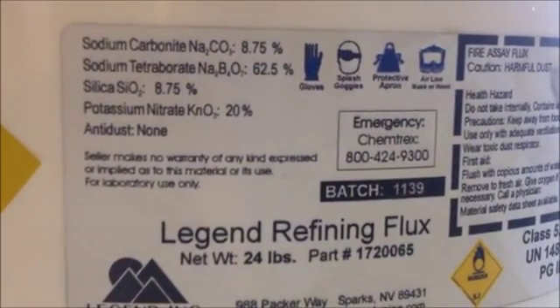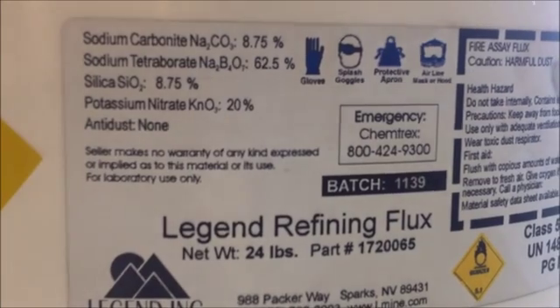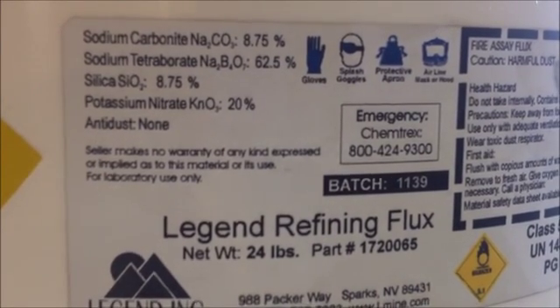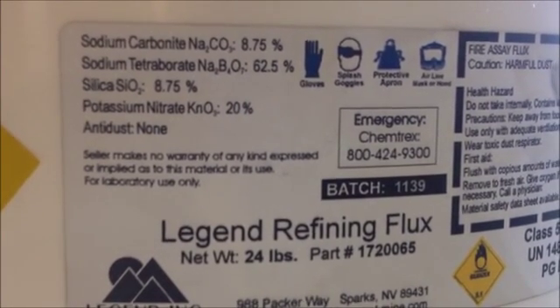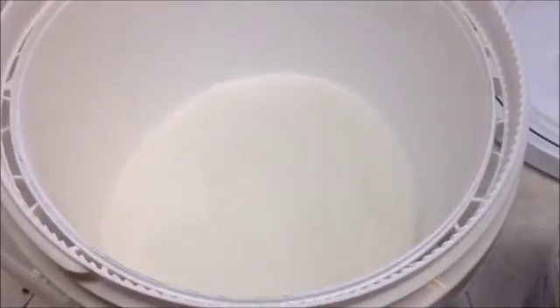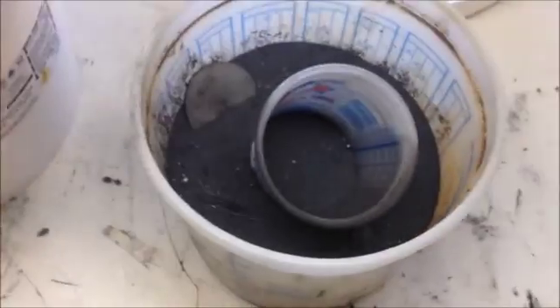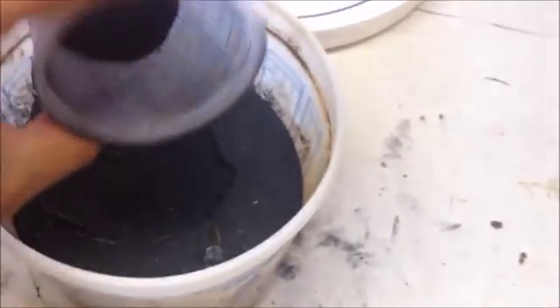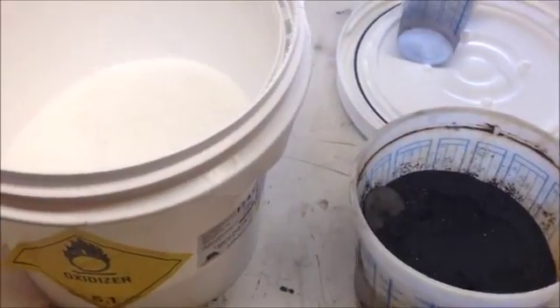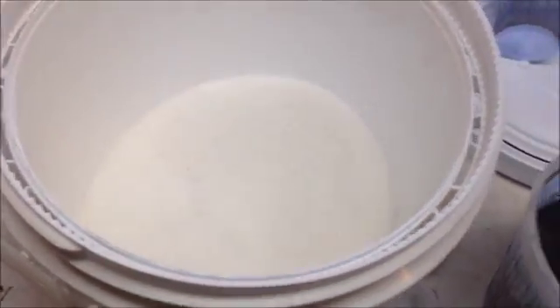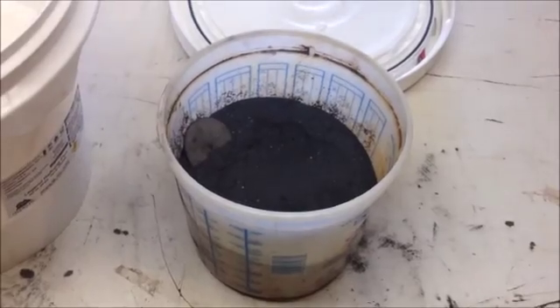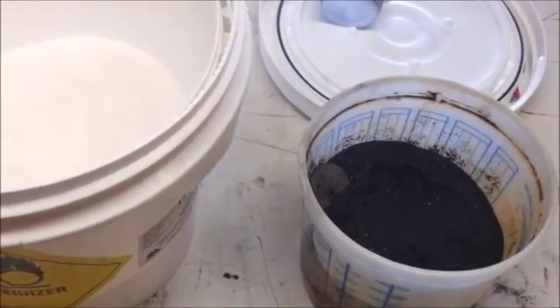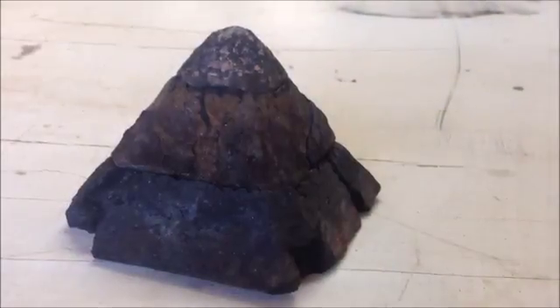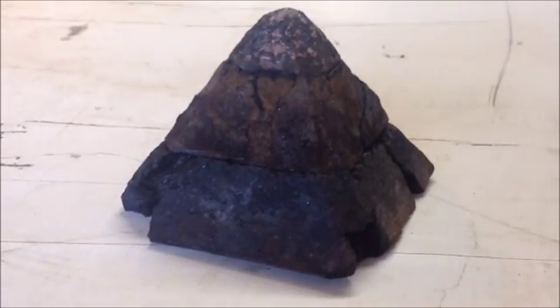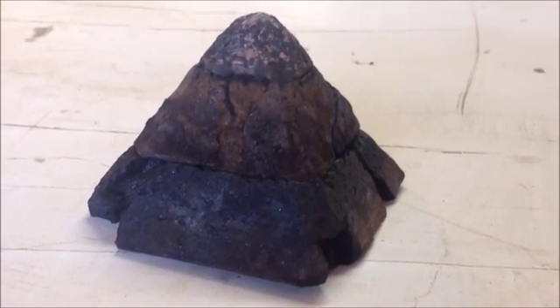So here's the composition of the potassium nitrate flux I'm going to be using to process the mat. And you can see there's quite a bit of borax in there, and I'm going to add a little more silica. So here's a look at our potassium nitrate flux, and here's some of the iron filings I'm going to be using. And I'm going to add about 1 part flux, 1 part iron shavings, and 1 part mat, and see how it goes.